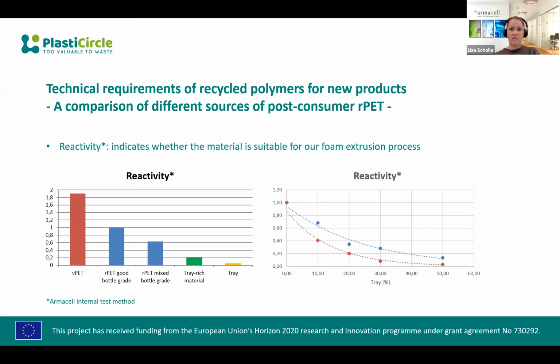Besides testing the IV and CEG, the focus was on testing the so-called reactivity. This is an Armacell internal test method that indicates whether the material is suitable for our foam extrusion process. The analysis of reactivity shows the same or even a clearer picture than the analysis of CEG and IV. So the pure tray material shows a very low reactivity, and also the tray-rich material has a low reactivity.